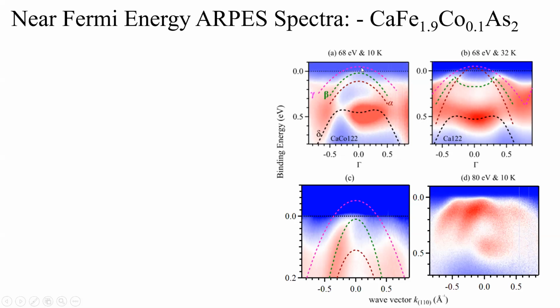In this case, we see a significant shift in the position of the bands, and this shift is expected in the sense that if you dope electrons in your compound, the states will be filled, and then since the states are filled, the Fermi energy will go up. However, the main problem is the position of these p states. Even if you dope electrons in your compound, the bands were expected to appear very close to each other. However, we see that in this case, the alpha band is much lower at this position, whereas the beta band is still close to the Fermi energy and the gamma band is still crossing the Fermi energy.